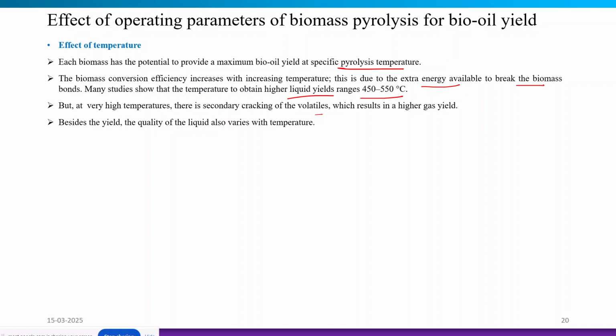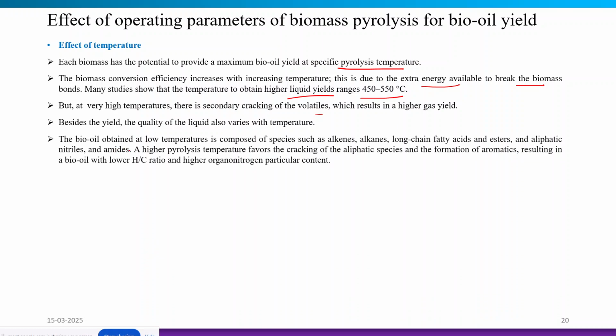Besides the yield, the quality of the liquid also varies with the temperature. Bio-oil obtained at a low temperature is composed of alkenes, long fatty acids, esters and aliphatic nitriles or amides. A higher pyrolysis temperature will favor the cracking of these aliphatic species and they form more aromatics, resulting in a lower H/C ratio of the bio-oil and higher organonitrogen content.